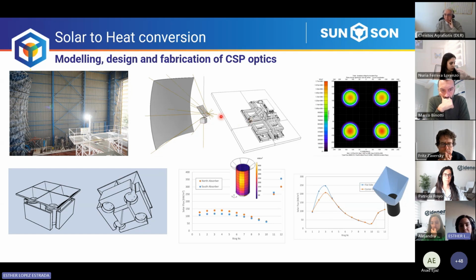And the reason why we do this is because by using this butterfly mirror, we can split the total irradiance into 4 different spots. Because according to our simulations, the irradiance level achieved in every spot should be high enough to achieve the temperatures that we target. So the shape and the size of this spot will fit the shape and the size of cylindrical absorbers. The cylindrical absorber is this black part here. And surrounding the 4 cylindrical absorbers, we will place the crucibles that contain the PCM. So here you can see 4 crucibles.